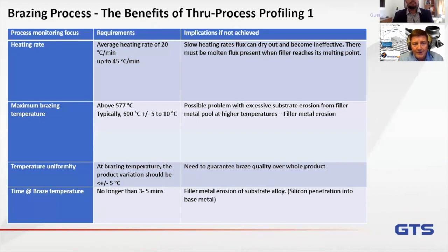The actual brazing temperature, the critical peak temperature of the profile itself, is obviously critical, and we're looking for uniformity. What we don't want to do is exceed that temperature too greatly, because then you may end up getting close to the aluminium melting temperature, and we can get what we call filler metal erosion, where the alloy metal starts to eat into the aluminium substrate surface itself.